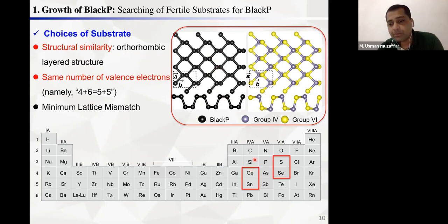To fulfill this condition, when we look into the periodic table, you can see group 4 to 6 compounds: GeS, GeSe, SnS and SnSe. They have a very similar structure to black phosphorene. They also have the same valence electron count, meaning the number of electrons in the outermost shell. Lying in the fourth and sixth groups, a whole unit cell has 10 electrons, which is equal to 2 times phosphorus, since phosphorus lies in the fifth group. So group 4 to 6 compounds fulfill this condition: an orthorhombic layered structure as well as similar valence electrons.